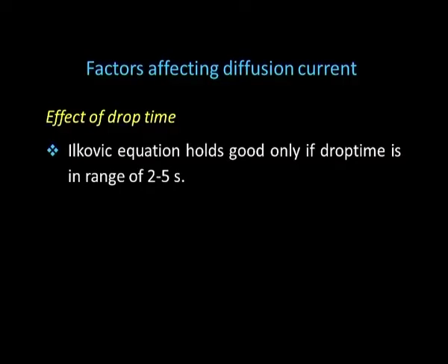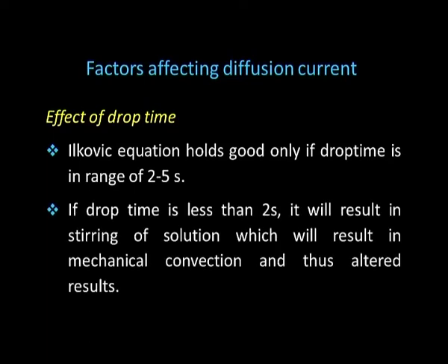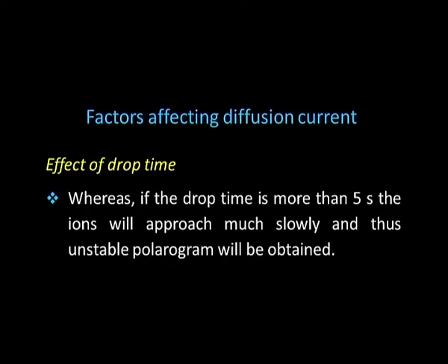Now, the question comes to consider the factors which affect diffusion current. The first is effect of drop time. There is a condition that Ilkovic equation holds good only if the drop time is in the range of about 2 to 5 seconds. If drop time is less than 2 seconds, it will result in stirring of the solution, which will result in mechanical convection, and thus changed results are observed. Now, if the drop time is more than 5 seconds, the ions will approach much slowly, and thus an unstable polarogram will be obtained.